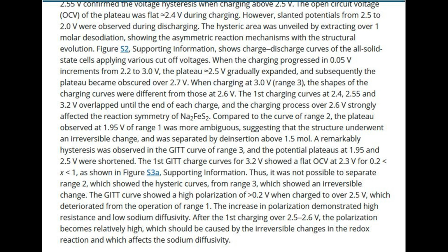Compared to the curve of range 2, the plateau observed at 1.95 V of range 1 was more ambiguous, suggesting that the structure underwent an irreversible change, and was separated by de-insertion above 1.5 mol. A remarkable hysteresis was observed in the GITT curve of range 3, and the potential plateaus at 1.95 and 2.5 V were shortened. The first GITT charge curves for 3.2 V showed a flat OCV at 2.3 V for 0 < x < 1, as shown in Figure S3a, supporting information.